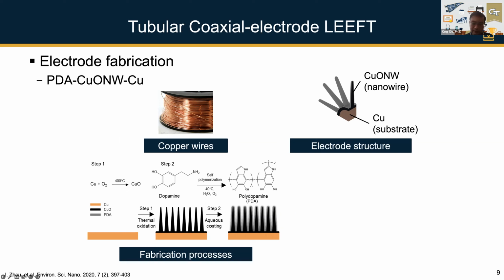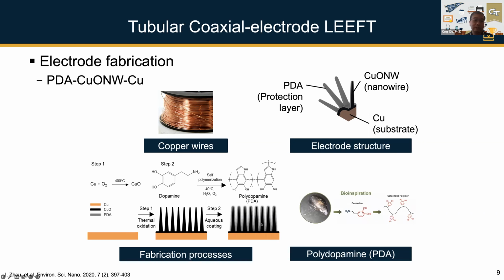And then we do another coating step, a polydopamine coating. Polydopamine comes from the monomer dopamine. This coating is also a very straightforward, very simple synthesis process. We prepare a dopamine solution, and then you just dip your material, in this case copper oxide nanowire modified copper, into this dopamine solution, and the dopamine will self-polymerize. It's also an oxidation process, at a certain temperature with oxygen. The dopamine will self-polymerize on the surface of the material, so eventually you form a very uniform thin layer of polydopamine on the surface. The purpose of this polydopamine coating is really to improve the stability of the electrode, to make sure it can last for a longer treatment time.